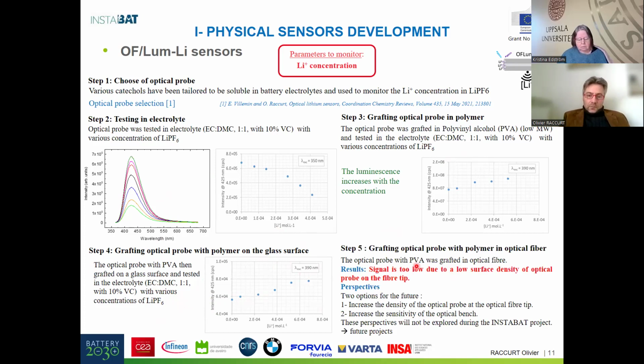But when we tried to graft this molecule at the end of the optical fiber, we see the signal, but the signal is very low, and it's not possible to use the sensor to monitor the lithium in the electrolyte at this time. Due to the very low signal, there is a lot of noise, and it's not possible to monitor precisely the concentration of lithium with the sensor actually.